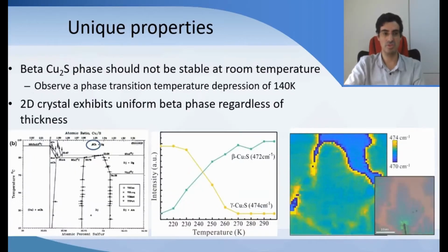The other interesting feature is that the thermodynamic phase that we're observing, beta Cu2S, is not supposed to be stable at room temperature. So we are doing these experiments slowly enough that we can assume adiabatic conditions, and we find that only over about 100 degrees would we expect beta Cu2S to be stable, and it should transform into gamma Cu2S under that temperature. But what we're seeing is that the phase change is only happening around 140 Kelvin below the